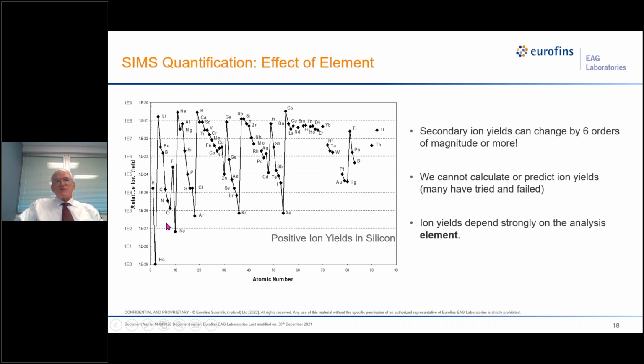So we need standards for all these different elements because they all have vastly different sensitivities. And as I was alluding to in the previous slide, if that wasn't bad enough, each element would require a standard in each different material. This boron here would require a standard in silicon and a standard in silicon germanium. And we have to have ways of providing accurate quantification as we cross from one layer to the next.